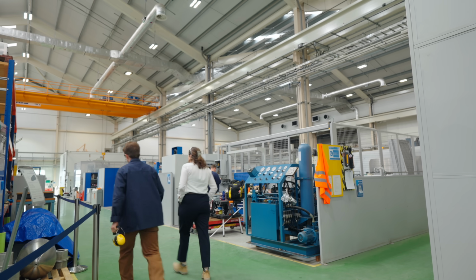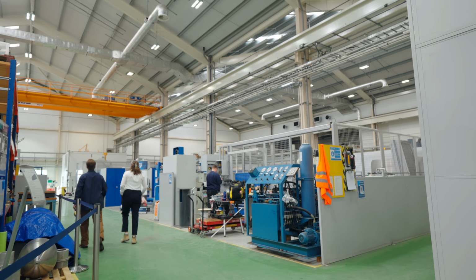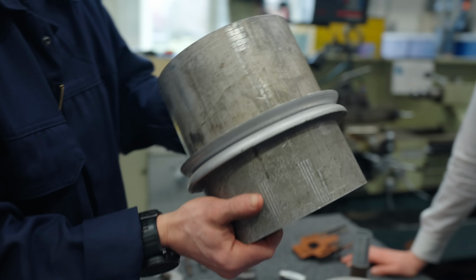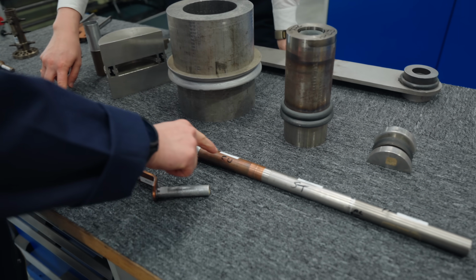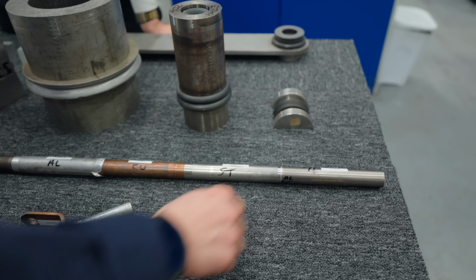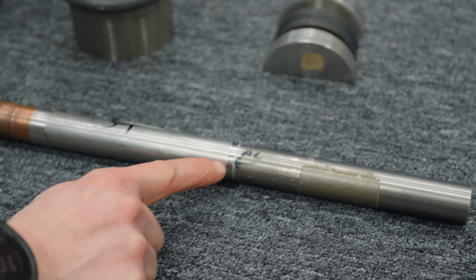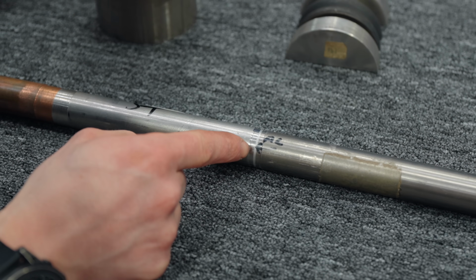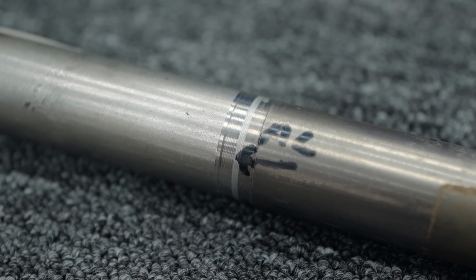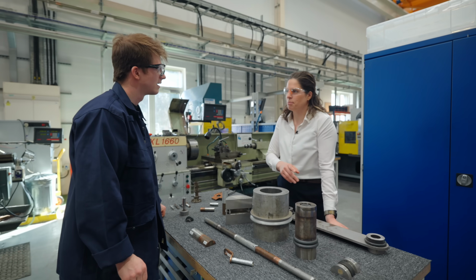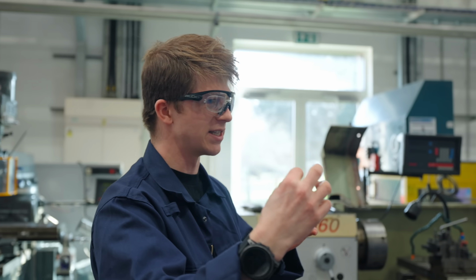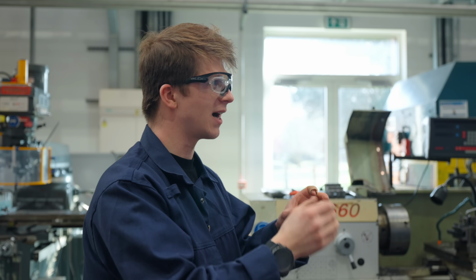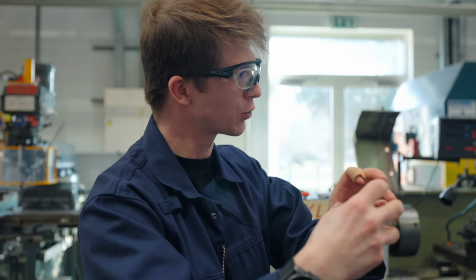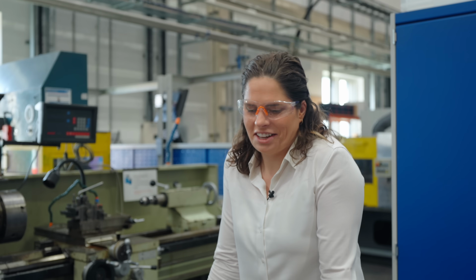Rotary friction welding. So these are some of our rotary friction welding samples. So stainless, mild steel, aluminium, copper, stainless, titanium. Oh, you're doing a stainless to titanium with an aluminium interlayer? Yeah, so even with friction welding, stainless is pretty hard to join to titanium. And I presume that aluminium interlayer is rotary friction welded onto one part, machined down, and then rotary friction welded together as the interlayer. Exactly like that, yeah.